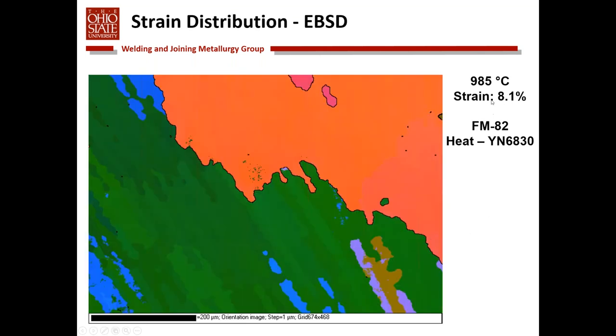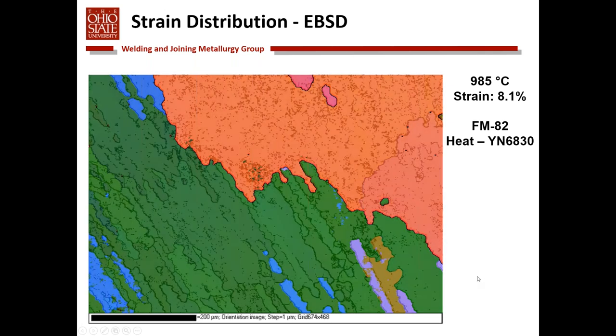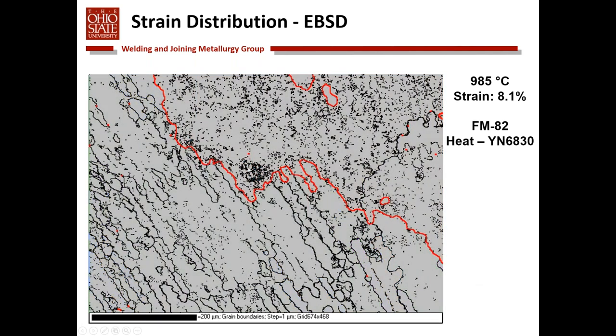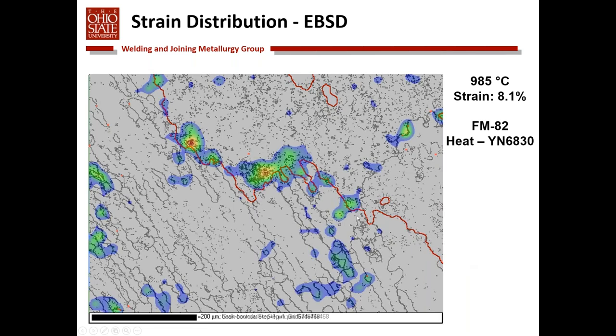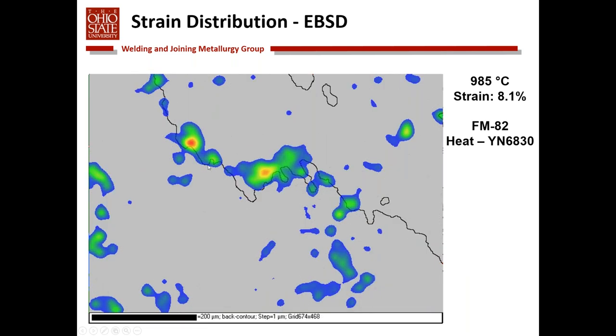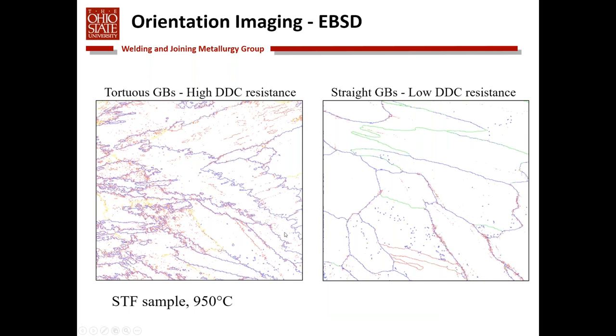Another example, at slightly lower strain, again, the raw data from the EBSD strain pattern, and again, the strain pattern color-coded that basically shows, again, that strain tends to build along the grain boundaries. So whatever we can do to make these boundaries, in this case, much more tortuous, we can basically increase its resistance to ductility dip cracking.